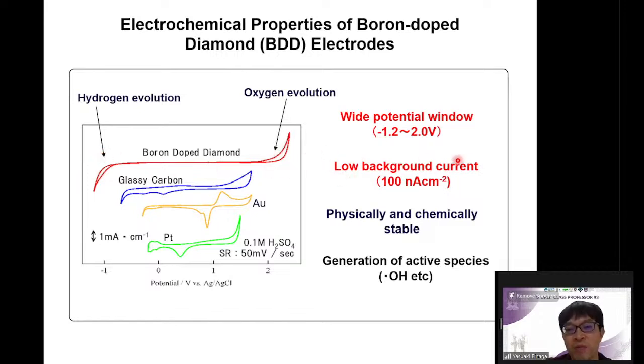Also the low background current is a very good point for electrochemical sensor application. In this region, inside the potential window, the background current is very, very small. So it means the signal-to-background ratio is very high, so it shows a very sensitive response. So this is the advantage. I explained it again. Okay, anyway.